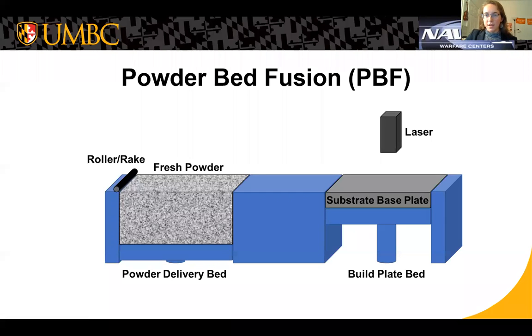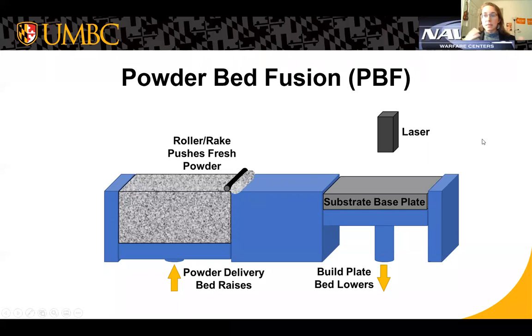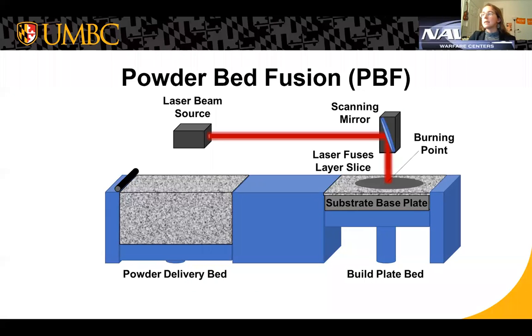The specific type of metal additive manufacturing that my work explores is powder bed fusion, which essentially involves two powder beds, one that's filled with fresh powder and one that starts off empty. As the process begins, a roller pushes fresh powder across a base plate. This is also done within a heated, argon-based chamber. So the build plate bed lowers, the powder delivery bed raises, and then the laser beam source hits a scanning mirror and fuses the first layer slice.